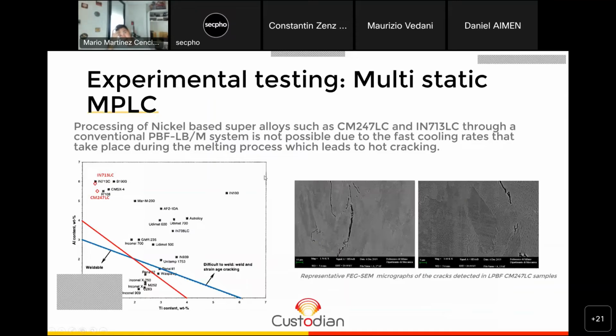So I will now move to the experimental testing, and first we will see some very brief slides of the multistatic, and then we will go to the dynamic shaper. And well, as Mauricio commented before, processing of those nickel-based superalloys, such as the CM247 and Inconel 713 low carbon, is not possible with powder bed fusion laser beam melting processes, because these systems normally work at room temperature, or we can nowadays find PBF systems that can preheat only up to low temperatures such as 400 or 500 degrees C. And so these high cooling rates lead to hot cracking while processing the materials.